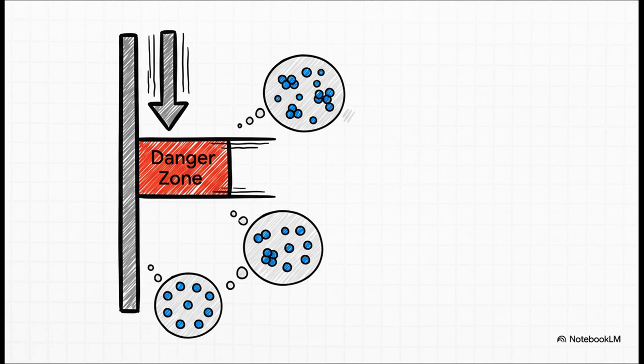For a serious aerospace alloy like 7075, that zone is between 400 and 290 degrees Celsius. The entire quench is just a frantic race against the clock to plummet through that zone before those weak structures can even think about forming.